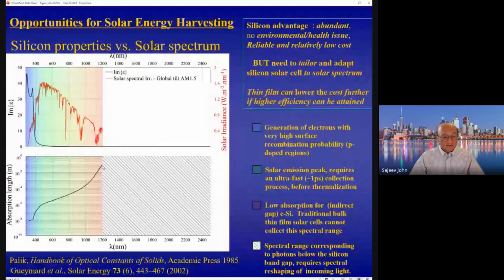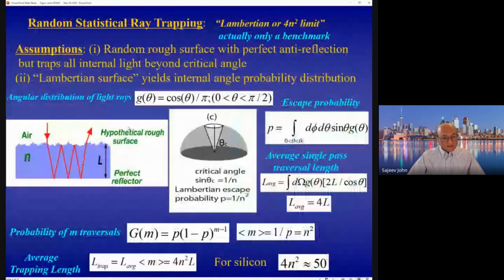And that creates a tremendous challenge in constructing an architecture that can absorb this broad spectrum of sunlight efficiently. And so this requires some sort of a light trapping mechanism in order to be able to capture this longer wavelength, especially near infrared sunlight. So the need for light trapping has long been known in solar cells, and in particular silicon solar cells. And this has a long and rich history. One of the approaches that people have considered from a long time back is something called statistical ray trapping, which pictures light not as a wave, but simply as a ray that can undergo reflection, refraction, etc.